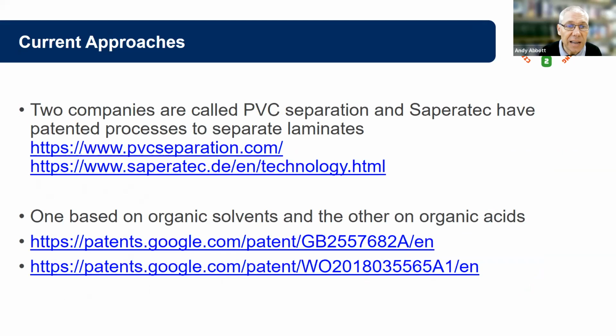So we've seen that there is some recycling of materials, although not commercially relevant at present. A lot of it is downcycled or goes into fillers in other applications. There are two processes on the net which talk about separation, and those are both covered by patents. It appears, although there's very little out there other than the patent information, that they're either based on organic solvents, which will dissolve the polymer components, leaving metallic components, and then the polymers are recovered by evaporating off the solvent. Or the other is to use an organic acid, which will attack the aluminium at the interface and then separate the materials that way. So that's what's been done so far, but there's very little data on that actually in the literature.